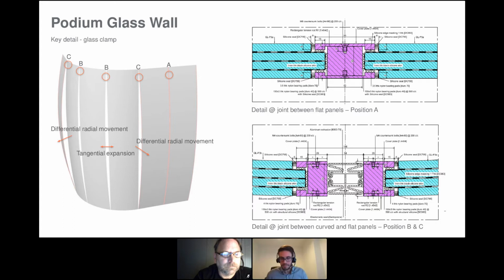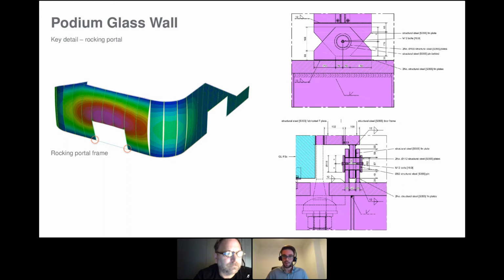Other key details are at the opening. Openings are always a bit of an issue when dealing with full height glass panels because of the differential stiffness that you will have between the frame and the glass itself. And it's even more exaggerated in this case because of the huge flexibility of the facade and the very high expected movements. So having a typical fixed portal frame, especially on the east elevation, which is the one where we have the full light glass panel, was basically impossible unless having an additional movement joint around the portal frame. That's because the differential stiffness between the frame and the very flexible glass panel would have generated very, very high peak stress all around the corner of the portal frame.